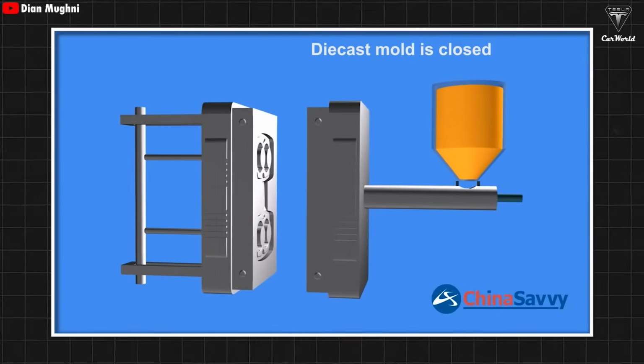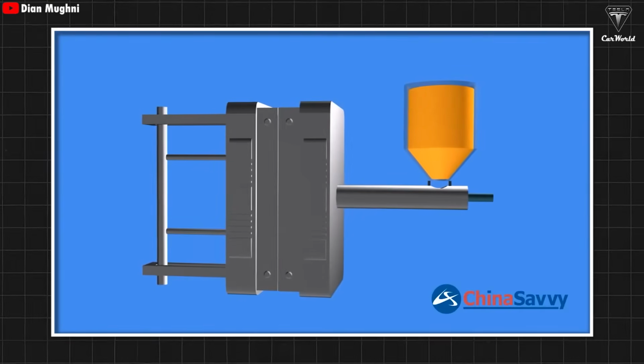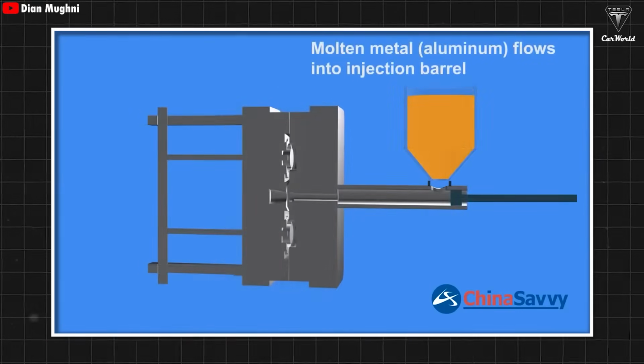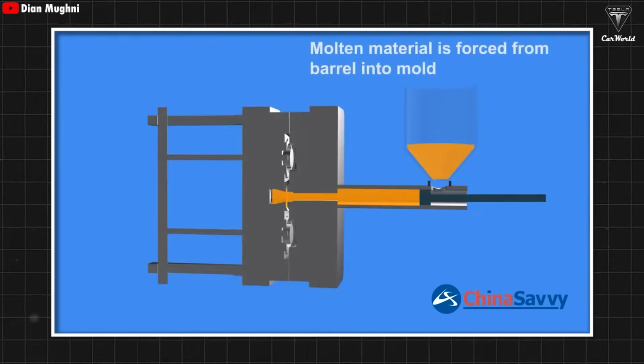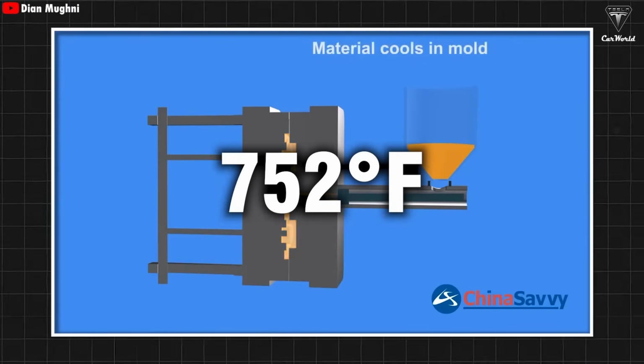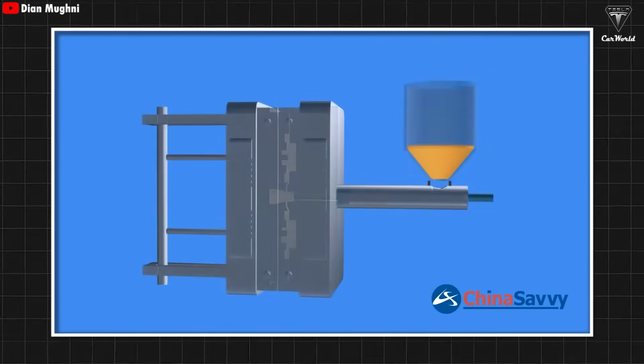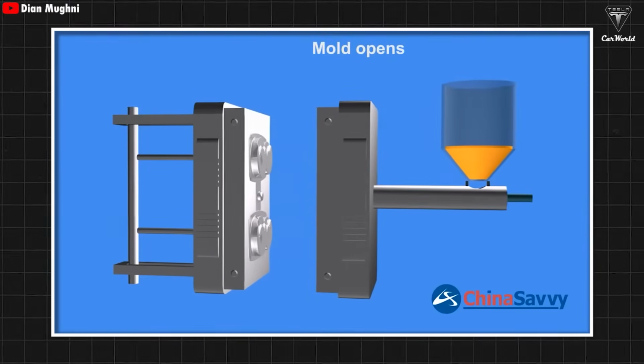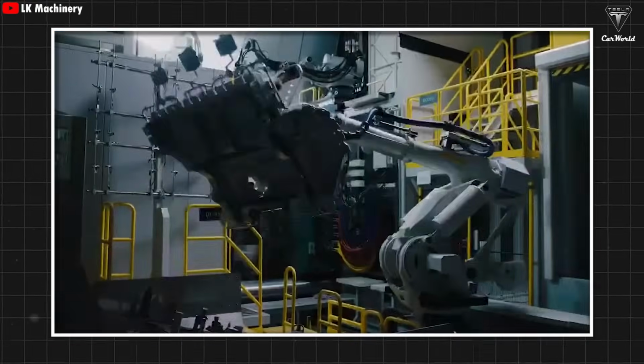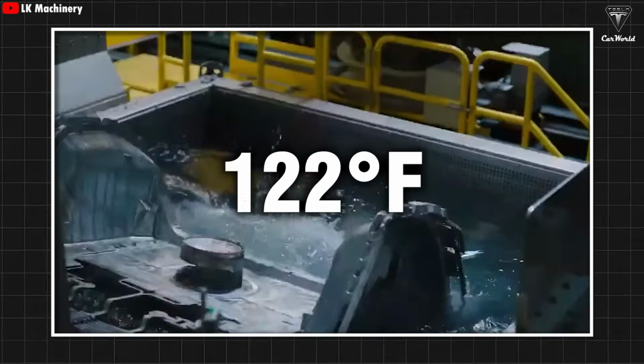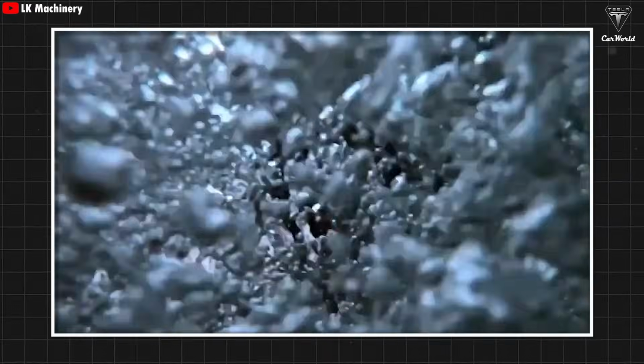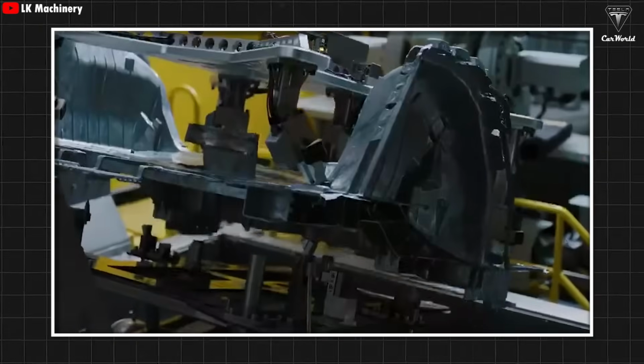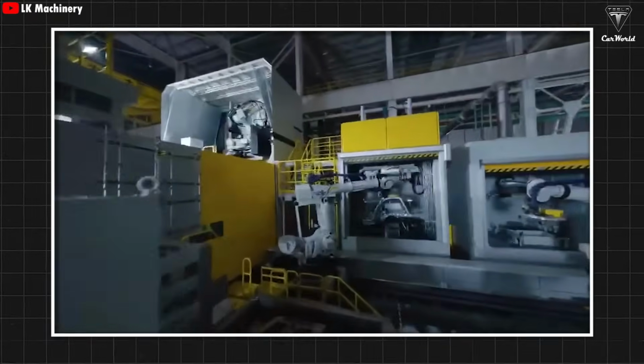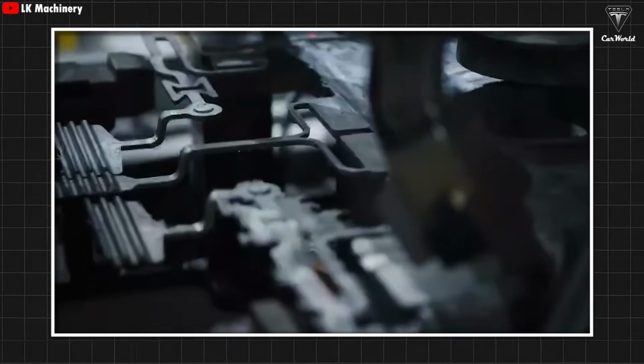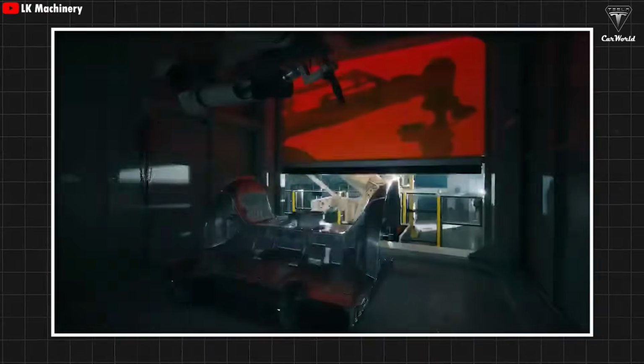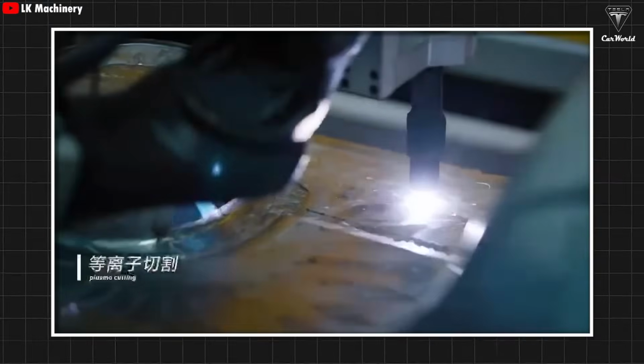After the aluminum is injected, it remains in the mold until it fully solidifies. The rough casting is ejected from the mold when it reaches about 752 degrees Fahrenheit and is immediately transferred to a cooling bath to rapidly reduce its temperature from 752 degrees Fahrenheit down to around 122 degrees Fahrenheit. This rapid cooling process not only effectively cools the material, but also helps eliminate certain defects that might form during solidification, while improving the aluminum's mechanical properties such as strength and hardness.